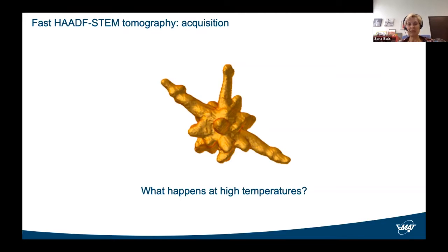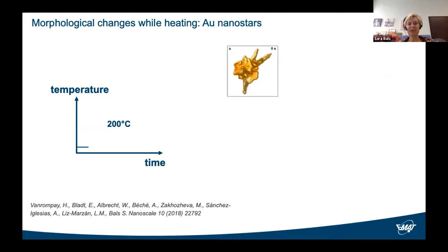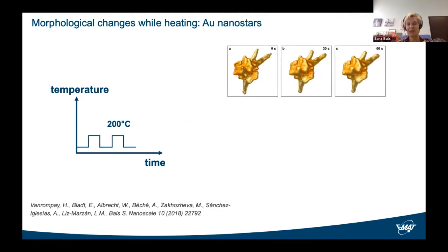So the experiment we performed is the following. We start first by performing an electron tomography experiment at room temperature. And we're going to be using a dedicated heating tomography holder. So everything can be done in situ in the electron microscope. Then we're going to heat our sample to 200 degrees Celsius. We keep it there for 30 seconds. We quench and we acquire another fast tomogram. We heat, we quench, and we acquire a fast tomogram.